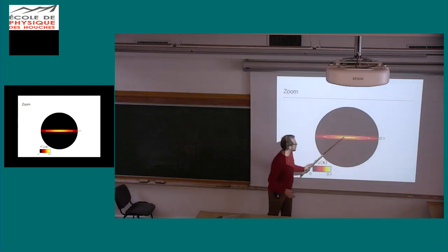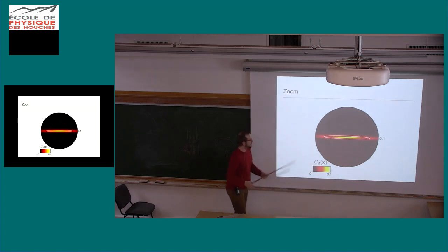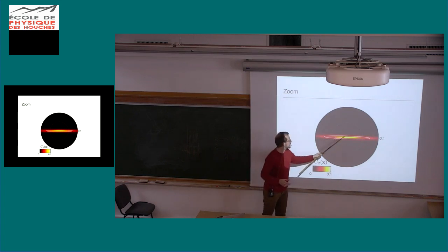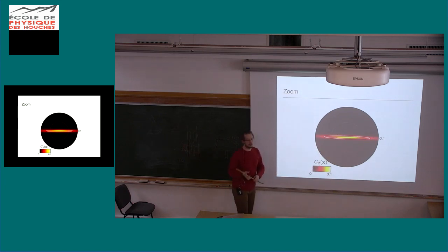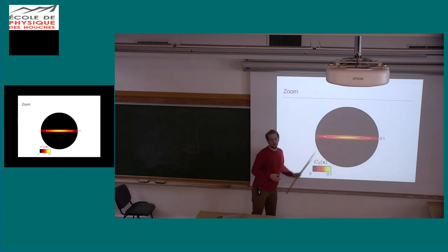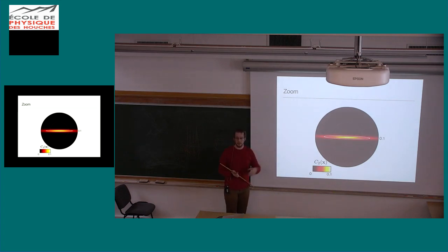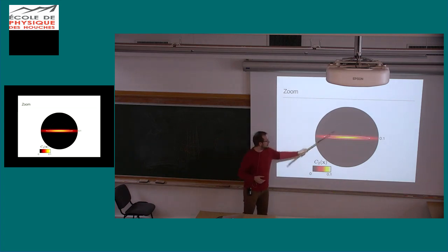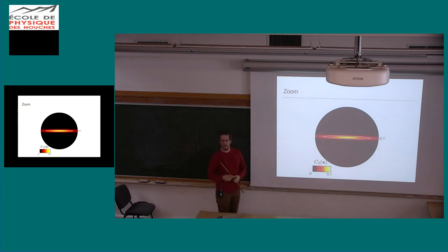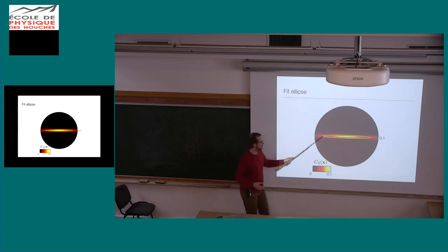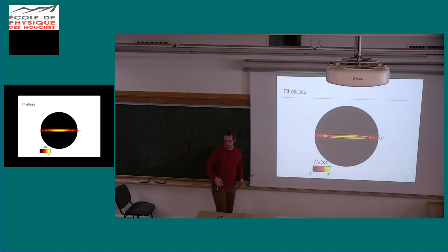you see, this is now from 0 to radius 0.1, and then still 360 degrees. You see this elongated shape. What I plot here is just the contour line where this function, when I fit an exponential function to that, falls off to 1 over e. And this is actually how the correlation length is defined. This way, I also recovered the correlation length that I put in originally in my medium. And this looks like an ellipse in the end, so I can just fit an ellipse to that and extract the 2 axes.